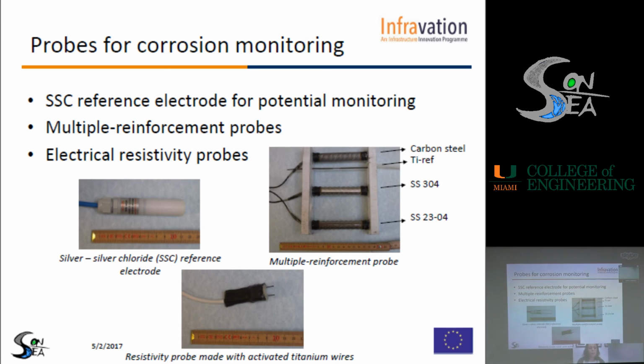And finally, we also used a resistivity probe that allows us to measure the electrical resistivity of the concrete. All these probes were embedded inside the concrete next to the reinforcement, so at the same depth as the reinforcement, at the same depth of the concrete cover.